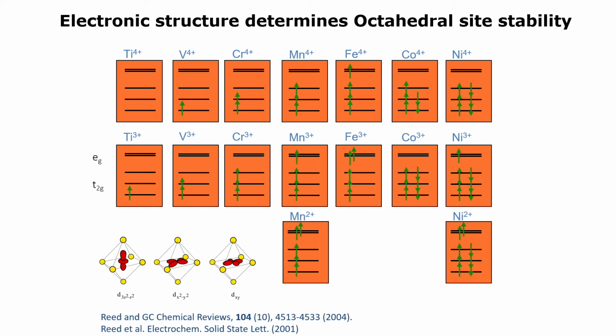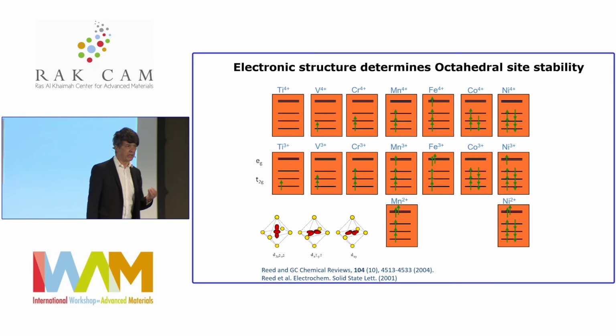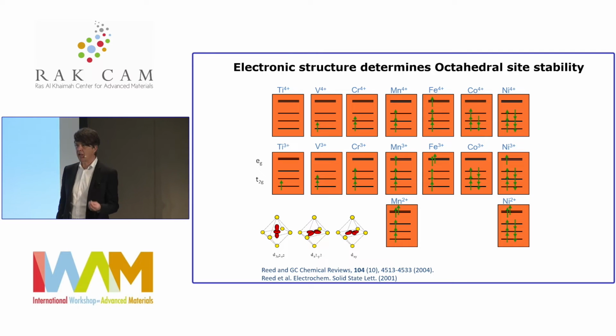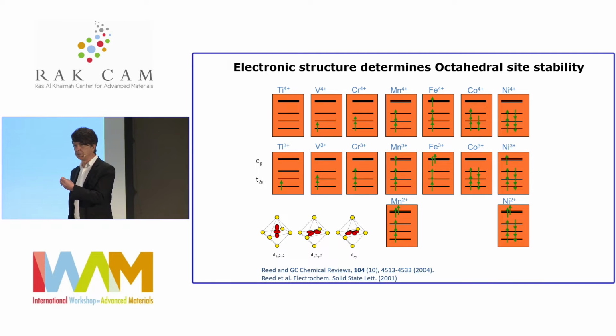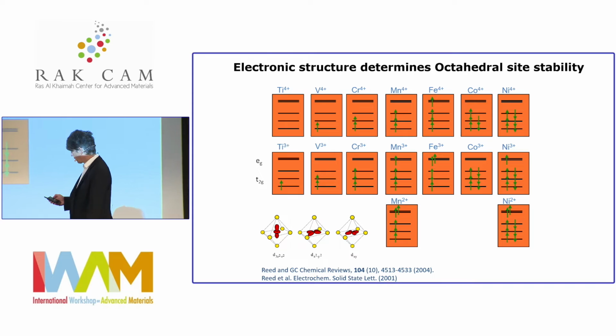Okay, so now my only piece of electronic structure theory: why only nickel and cobalt? Well, it turns out you have to prevent these elements from diffusion, and they sit in an octahedral site. So what you really want is an element that has very strong ligand preference for octahedral sites and hates tetrahedral sites, which is the intermediate site. So you do a bit of electronic structure theory, right?